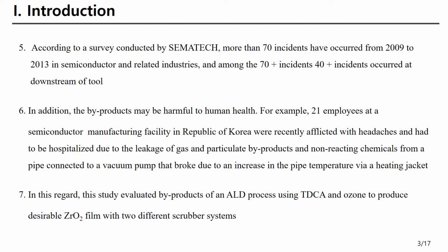According to a survey conducted by SEMATECH, more than 70 incidents have occurred during 5 years in semiconductor and related industrial, and among the 70+, 40+ incidents occurred at downstream of tool. In addition, the byproducts may be harmful to human health. For example, 21 employees at the semiconductor manufacturing facilities in the Republic of Korea were recently afflicted with headache and had to be hospitalized due to the leakage of gas and particulate byproducts and non-reacting chemicals from a pipe connected to a vacuum pump that broke due to an increase in the pipe temperature via heating jacket.